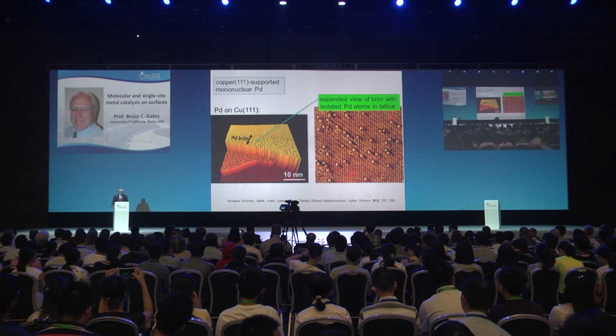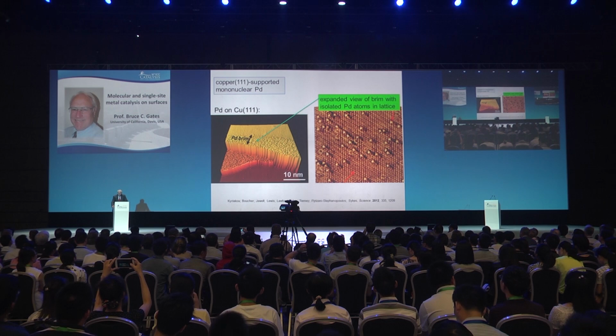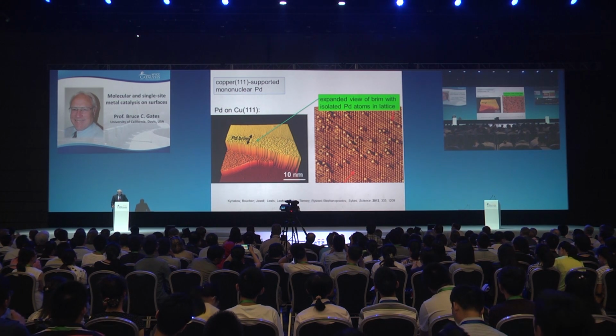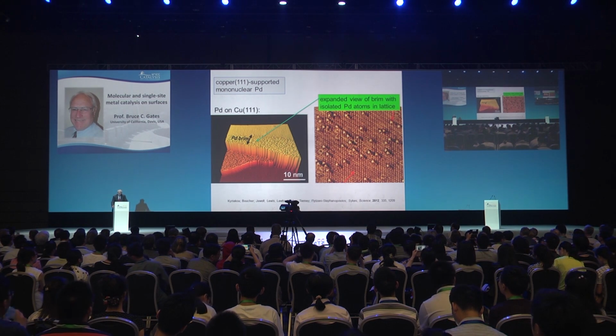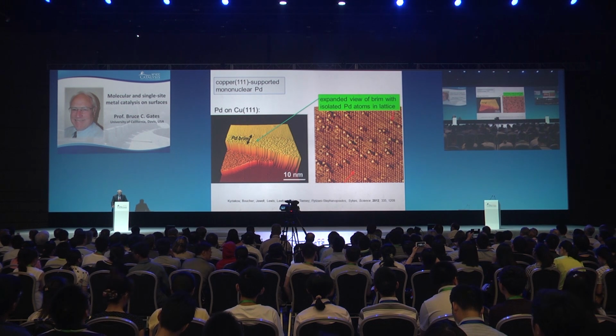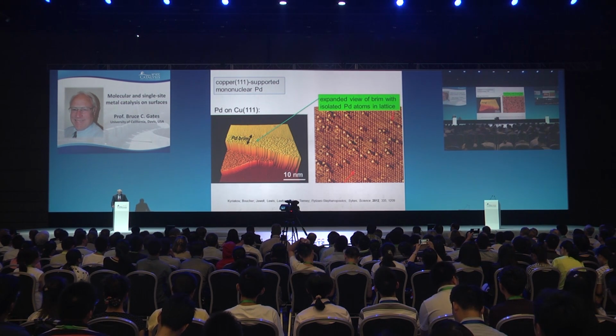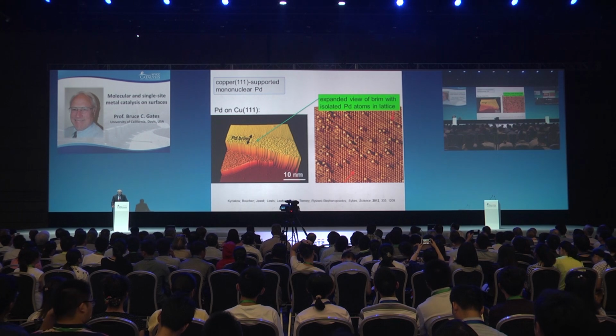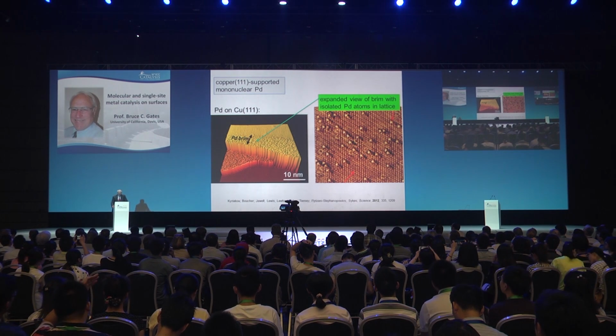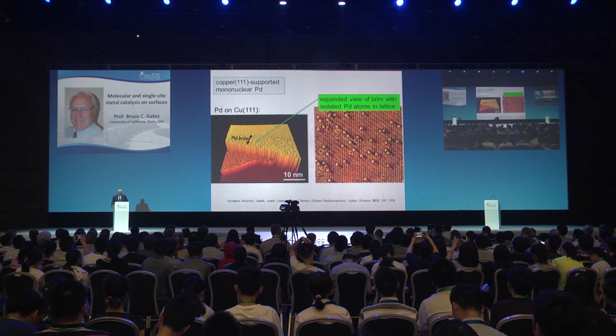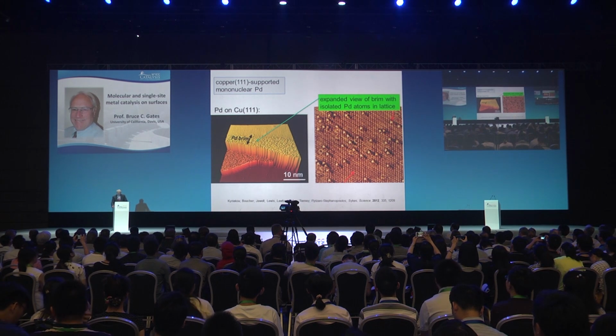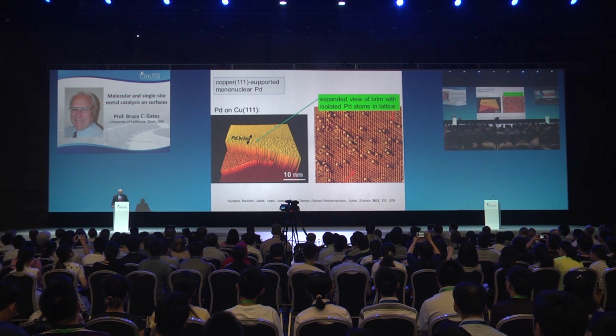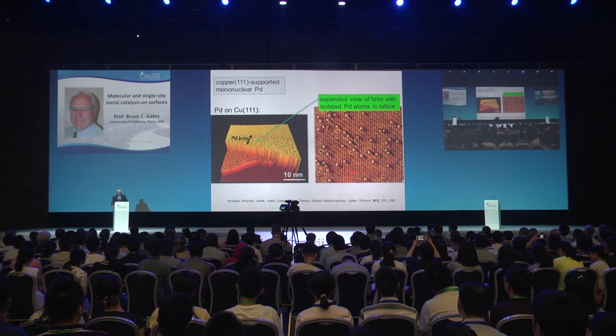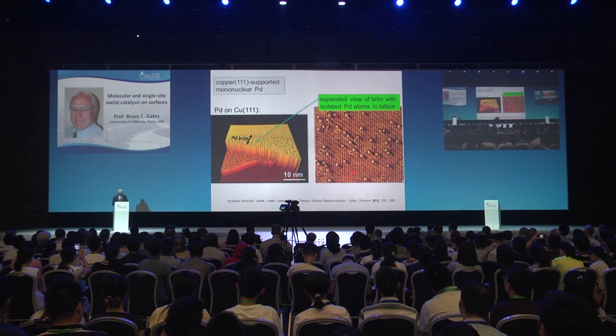Let's consider the support to be a metal. How about single crystal copper? Deposition of palladium onto that under the right conditions gives site-isolated palladium. They're mononuclear species, and they're good catalysts—they do hydrogenation. So we've got a metal as a support and a supported metal catalyst that's truly mononuclear.